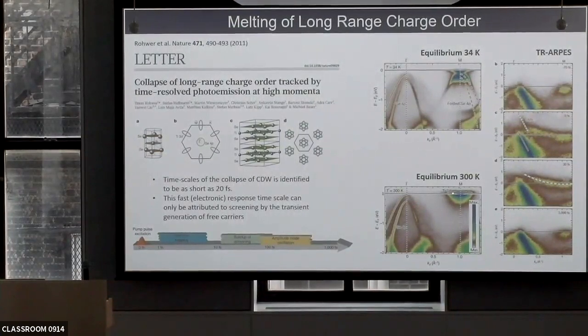In the high temperature phase, you have a rather well-defined band structure with two symmetry points which are distinct. When you go below a phase transition, a CDW type phase transition, these two points become equivalent, and so you start seeing folding of bands due to the CDW. Now the idea is to come in with a pulse, and so this data basically corresponds to this region before the pulse comes in. You cannot read the number, but it's zero femtoseconds, when a probe and pump pulse come in together onto the sample. And so what you can see is a variation in the band structure.